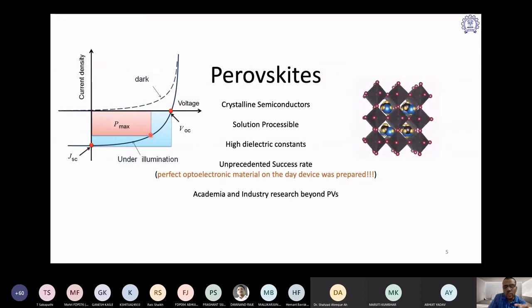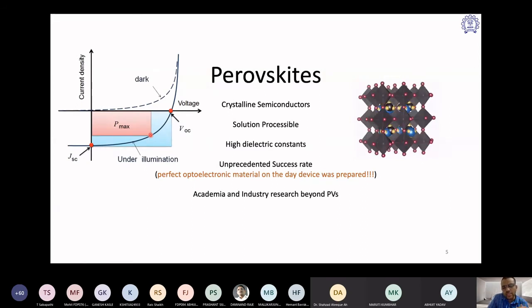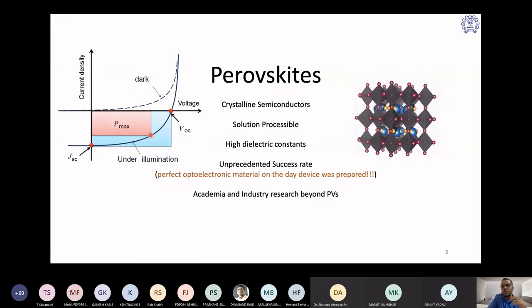At that current density, the solar cell is getting heated up, and the temperature can go easily in the range of 65 to 70 degrees Celsius under one sun condition. And at that temperature, if you are running your device continuously for a few hours, and if your material is inherently unstable with temperature, then your solar cell will degrade very rapidly. Hence you need to ensure that your semiconducting material has its own inherent stability first. Thermal stability is one of the major concerns.